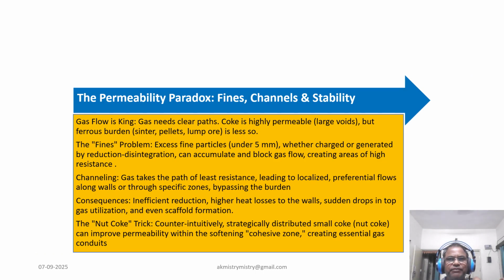For a blast furnace to operate efficiently, hot gas must ascend uniformly through alternating layers of coke and iron ore. But here is the paradox. The permeability of this layer is constantly under threat. Too many fines, either from raw material or generated during reduction, can cluster and form dense, impermeable zones. This forces the hot gas to channel, taking shortcuts often along the furnace walls, bypassing the very ore it needs to reduce. The consequences are severe: wasted energy, poor reduction, and potential damage to the furnace lining.